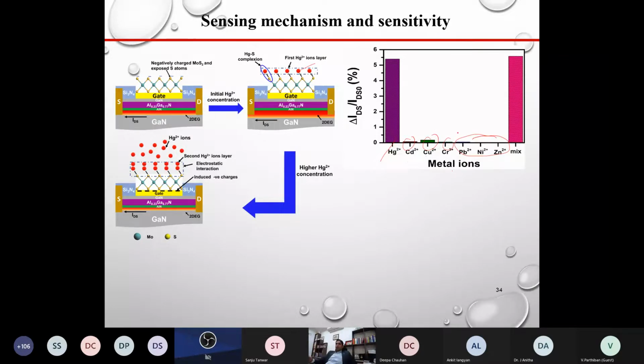In the cross selectivity, we have to mix all these ions together, because in water we don't know what ions are present. So we mix all the ions together, and then check how much change in the current there is. The mixed ions response is almost equal to the mercury ions response. That means this response is coming only from the mercury ions. Sensitivity is very good, around 0.64 microampere per ppb.